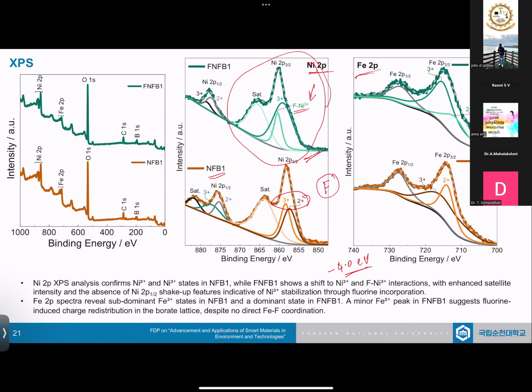That may be the reason, because there is a much higher number of nickel atoms present in the system when compared to the iron. Maybe because of that, or it has much better affinity in enabling such reactions. But we also can see that the iron has also been altered. So we can't conclude that the nickel is being bonded to fluorine just by vaguely trying to understand XPS.